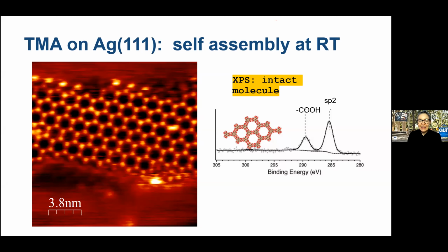What we determined was that we had begun to deprotonate the molecule after the annealing to 155 degrees with the ionic hydrogen bonded phase. This shows up as a second spectral contribution in between the carboxylic contribution and the primary peak. So this growth of a second peak, which is about 3.5, a little more, 3.8 electron volts above the primary peak, corresponds to the formation of carboxylate, COO minus. So this is our deprotonated segment of the molecule. And what we were able to do was to observe that the non-periodic phase had a deprotonation somewhere between 25% and about 75%, and that when it was 100% deprotonated, we formed only the knitted pinwheel phase.